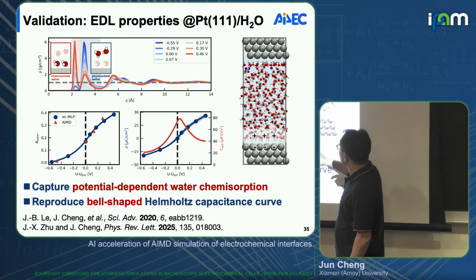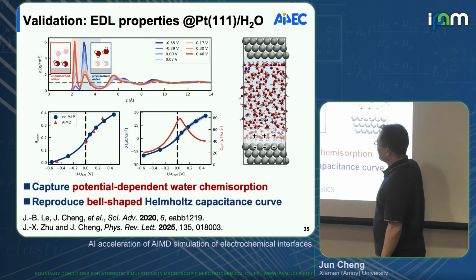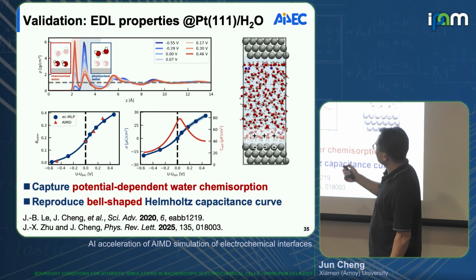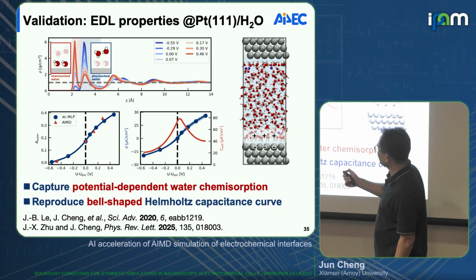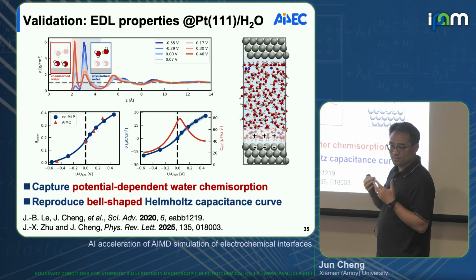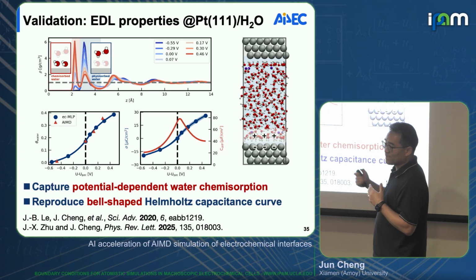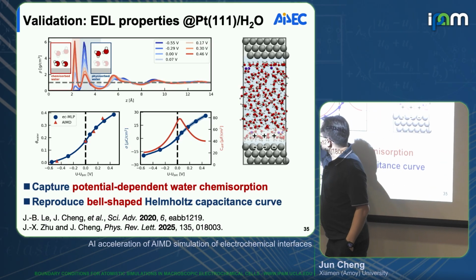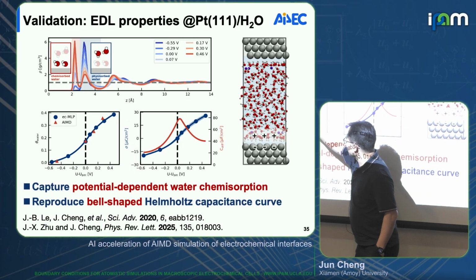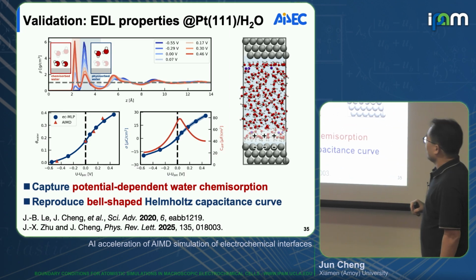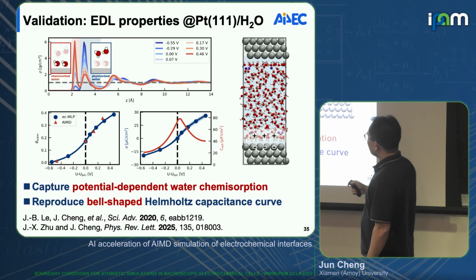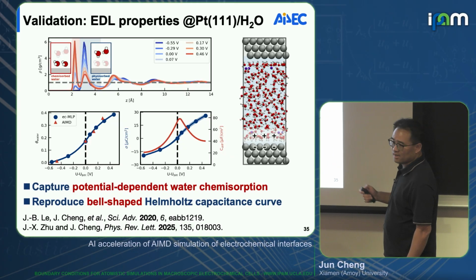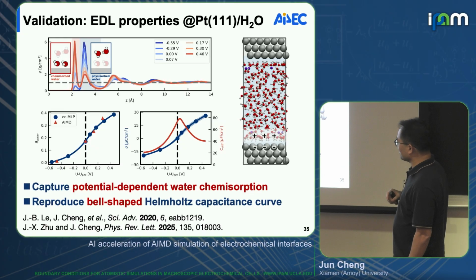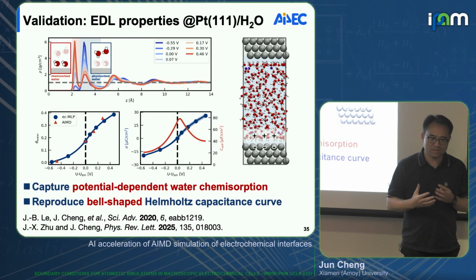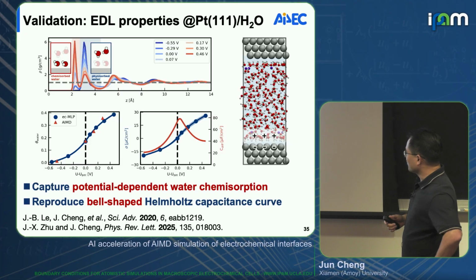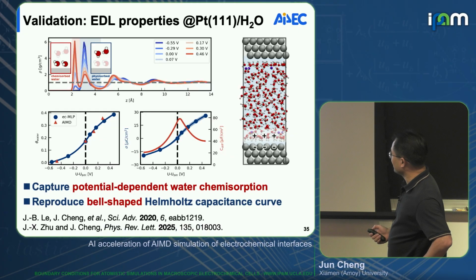Just the last slides, to quickly show, with this machine learning potential we call ECMLP. First of all, when we change the surface charge density and the potential, you can see the first peak is due to the chemisorption: the coverage of chemisorbed water changes with the potential. This reproduces the blue dots from the machine learning part, and the red triangles are from the AIMD simulation. It fits well. It also gives you this bell-shaped Helmholtz capacitance, reproducing the ab initio molecular dynamics result. I want to point out that, to me, it is important to capture both the electronic structure and the adsorption dynamics with this machine learning potential.